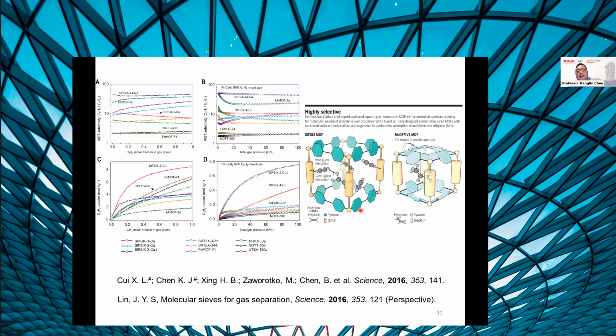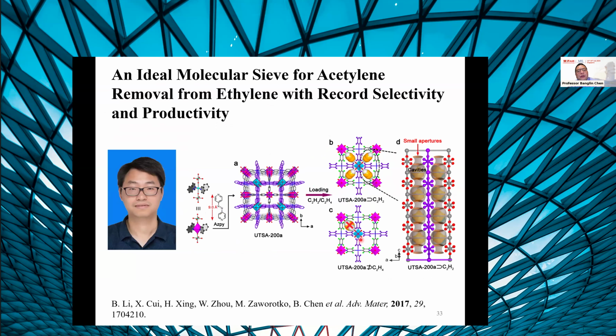And this certainly is an ideal material for acetylene and ethylene separations. Not only that, reticular chemistry allows us to use an even shorter organic linker. Here the principal one has a carbon-carbon triple bond, linear. The linker is a little bit longer than this. So using this shorter organic linker, you will see that the pore size becomes a little bit smaller. Now it can completely block ethylene, but still allow access of acetylene.